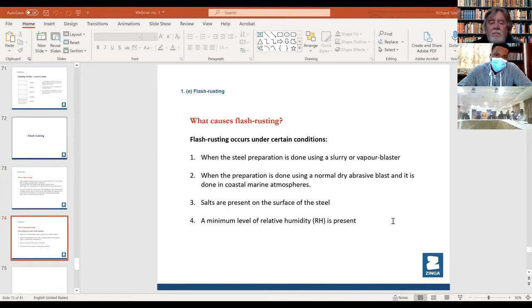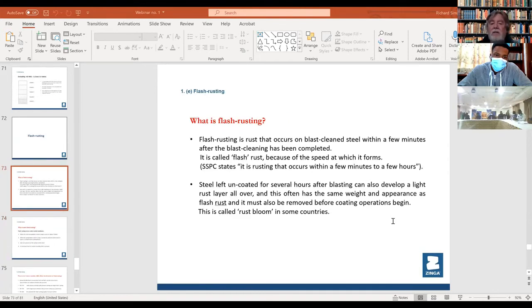Flash rusting. Okay, flash rusting occurs quickly. So you might be blasting, I've seen it in Mombasa and Tokaradi. You blast clean, it's a very humid day. You have high humidity levels in the atmosphere, it can be over 80% some days. And then you see it's flash rusting. Little spots start appearing after 1 hour, 2 hours. And normally we say try to overcoat the metalwork within an hour if possible.